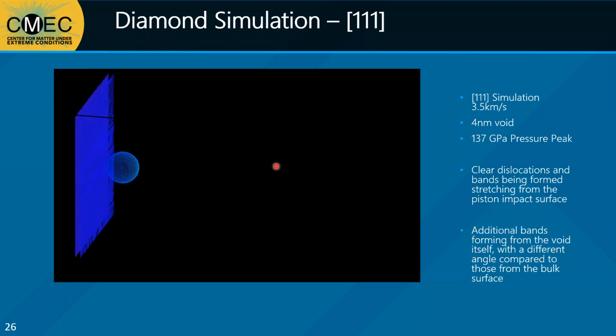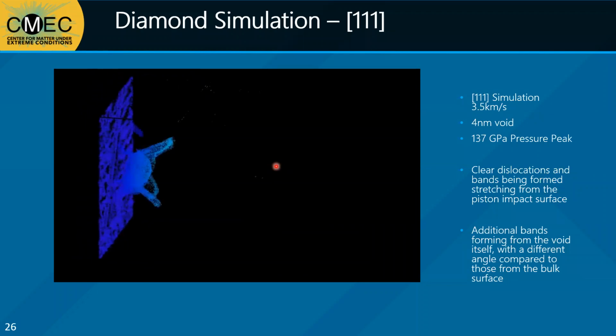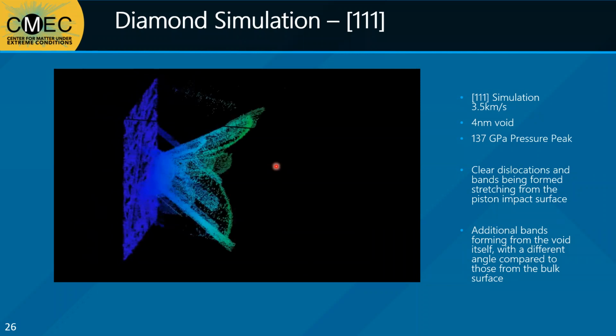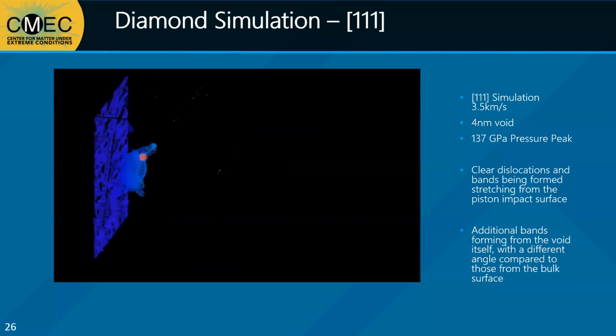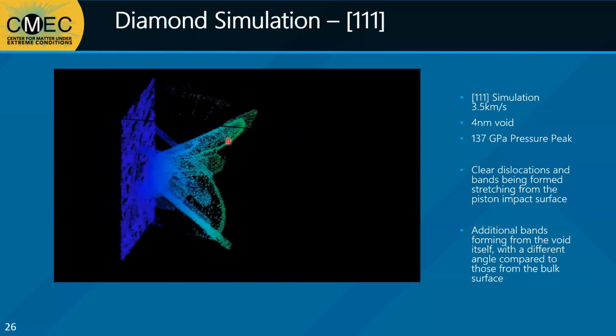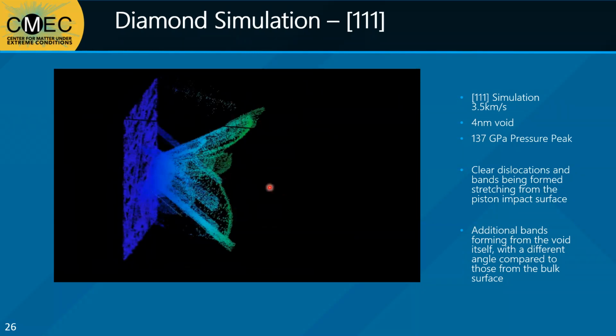This three-dimensional view of only the non-diamond atoms in the 111 shock simulation shows what is happening. We have three sets of rectangular bands emanating from the void, seen here, here, and here, which are threefold symmetric about the void. And we have two sets of half loops connecting these three bands. We also still have some of these rectangular bands coming out from the planar impact surface at the same angle and direction as the band emanating from the bottom of the void here. Notably, there is a third half loop that is missing from this simulation.